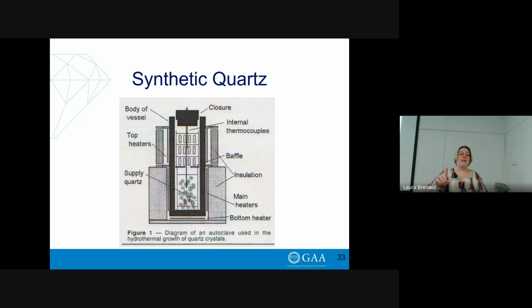plate through the center. If we hand around again the blue crystal that's in Adele's hand, you can see at one end of the crystal, it's got a tiny little bit of wire. And if you look down the center of the crystal, it's a light blue color, but it has a colorless plane right through the center. So that colorless plane is a seed plate. That seed plate can be made from either synthetic quartz or from natural quartz. But the feedstock that's placed in the base of the autoclave is usually natural material that's of a very high quality and has been cleaned to have any impurities removed.